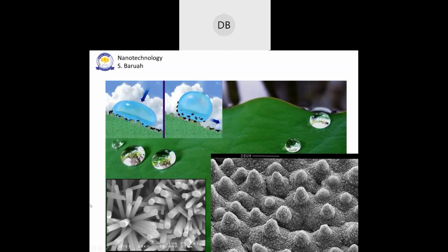Okay, because if I put a water droplet here, you see there are a lot of vacant spaces. It will touch this, maybe this, but there are so many other spaces that are vacant. And you see the scale bar, this is 1 micrometer. So these rods are roughly about 500 nanometers in diameter. And then we did some studies on these. We tried to see what happens when we put water droplets.